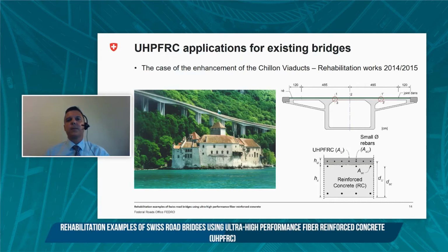They consist of variable height box girders by post-tensioning segmental construction with epoxy glued joints and spanning between 92 and 104 meters at a total length of 2,120 meters. In 2012, during rehabilitation works on the viaducts, early signs of the alkali aggregate reaction were discovered in the concrete. In later stages, this reaction could lead to deterioration of the concrete compressive strength, which would mean an insufficient structural safety for the resistance of the bridge at ultimate limit state and even worse at serviceability limit state.